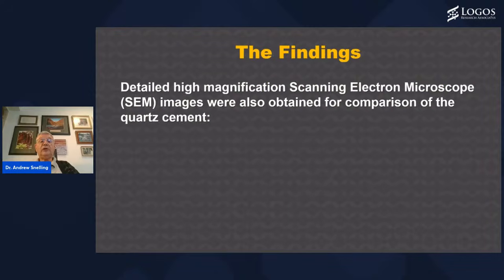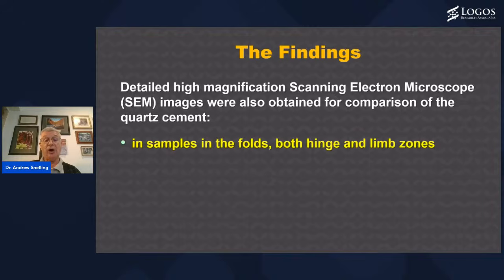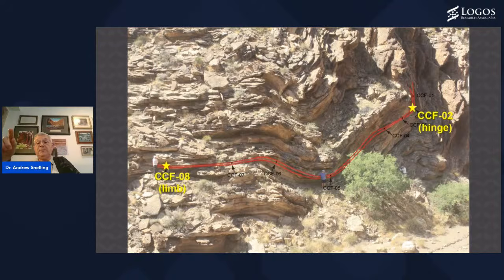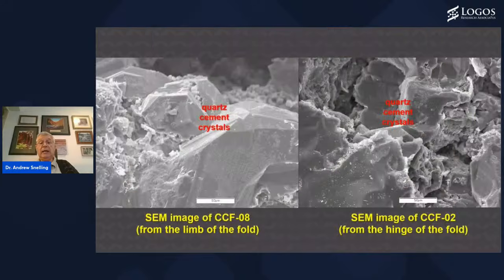Furthermore, detailed high magnification scan electron microscope images were obtained to look at the quartz cement in samples in the folds, both hinge and limb zone samples. And so here we see hinge zone sample 2 and limb zone sample 8 from this bed that we traced through the fold. Okay, here under the scan electron microscope, we see the pristine crystals of the quartz cement. Very well illustrated on the left.